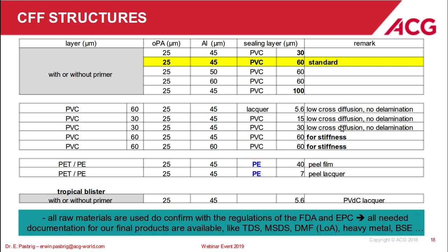The next part of the table you see is a four-layer laminate with PVC on the outer side. We recently brought onto the market the cold form laminates, four-layer with heat seal lacquer on the inner side at 7 GSM, so because of the density it's 5.6 micrometer. Then we have 15 micrometer and 30 micrometer. And you see on the outer side, we have a stiffening layer made from PVC. In case of the lacquer, it is 60 micrometer or 40 micrometer. 15 PVC at 30 micrometer and 30 micrometer both sides, 30 micrometer PVC. This material has the additional advantage, besides no cross-migration, that there's no primer, but there's the same level of delamination resistance compared to the three-layer structures with primer.